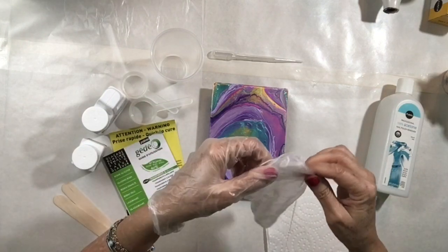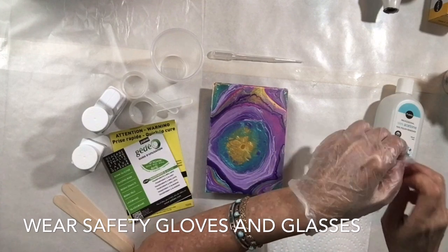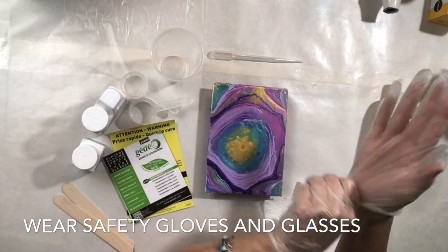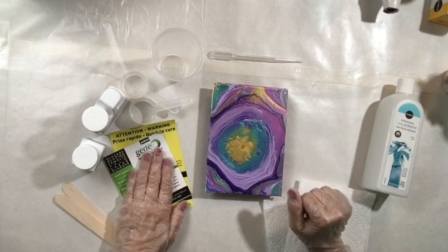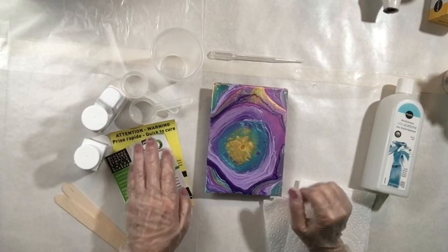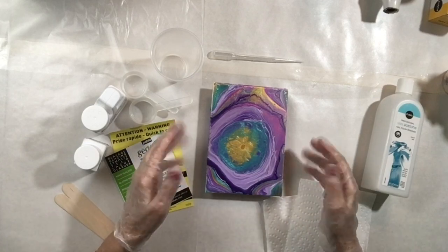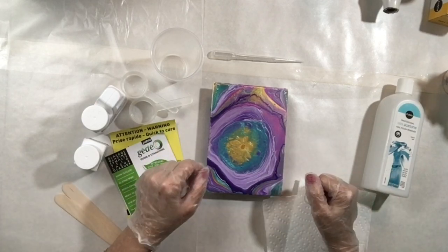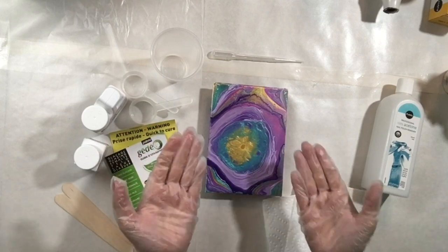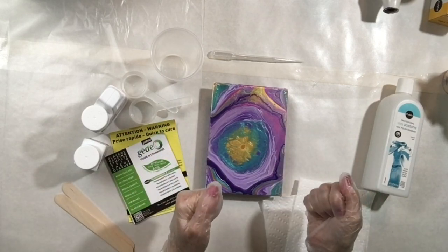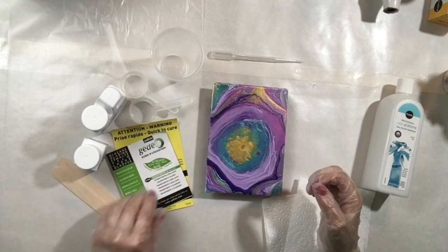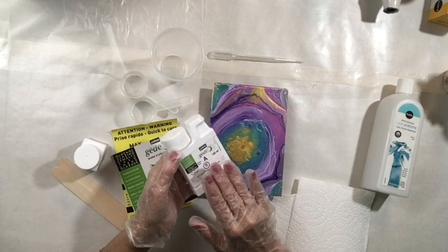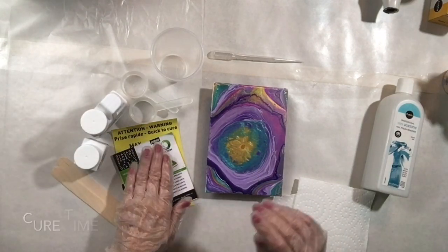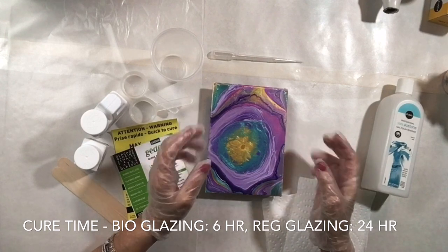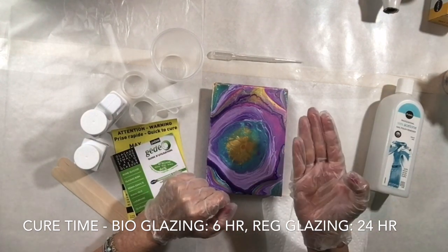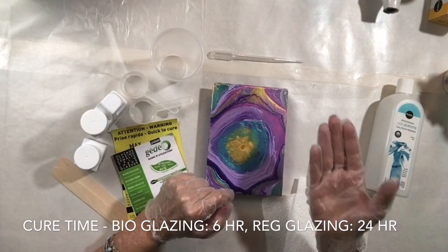Noticed that some people on the internet do not wear gloves when they mix their resin. I recommend that you always wear gloves, and also with this bioresin quick cure and any quick cure resin, you're going to find that because it cures quickly, it is going to heat up fast. And if you don't wear gloves, you're going to feel a burning sensation on your hands if any of it gets on your hands. Now, another thing about this quick acting glazing resin is that it's going to cure in about 6 hours. So a normal resin, like the other version of the glazing resin, will take about 24 hours to cure.